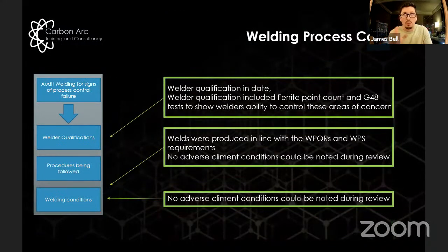One reason we could have lower or incorrect ferrite results is we've lost control of our welding process. Either the welders aren't welding correctly or it's not in line with our qualification data. Let's have a look. So we basically did a huge audit of our welding systems, and again, found enough pointers in the right direction to say, we're okay. Our welders are qualified, they're working in line with their requirements. We sent some samples for G48 testing as part of their qualification. We knew they could produce what they needed to do.